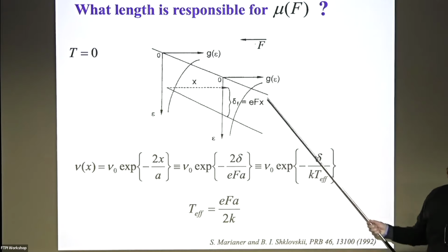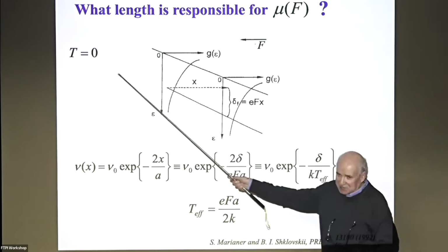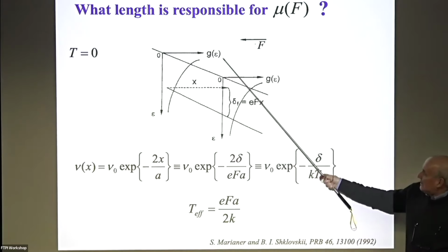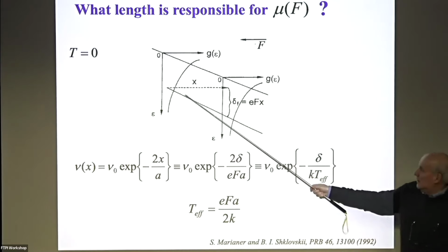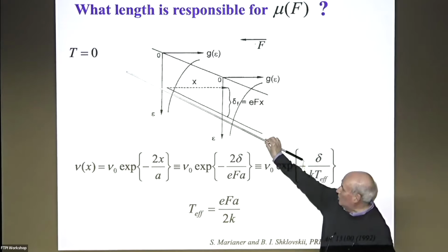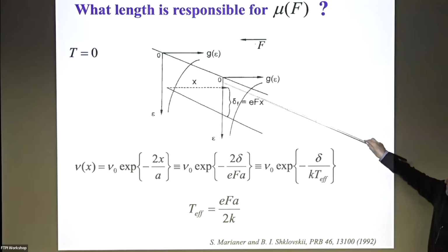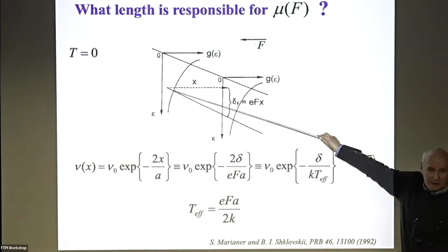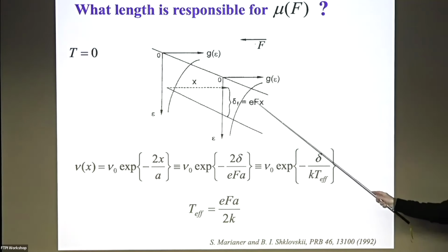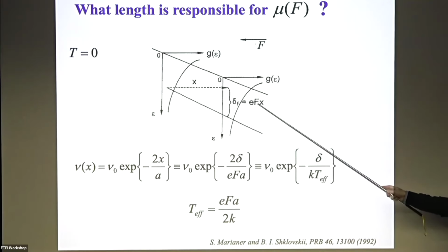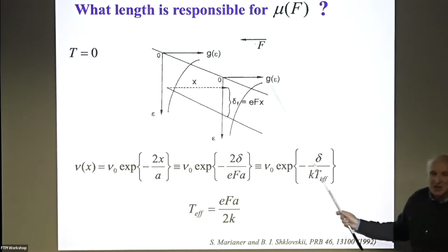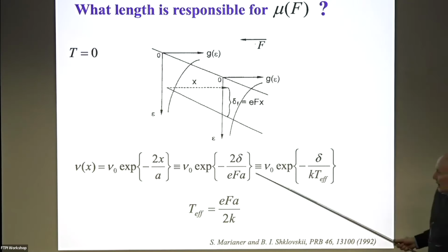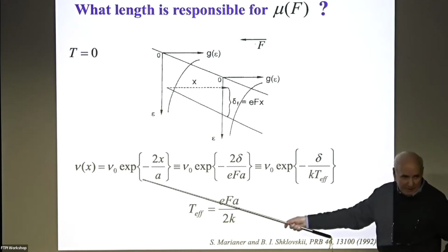Yesterday, all the students already informed us about it, so let's take temperature 0. Okay, then what happens? Let's take steeply decaying density of states. So electron tunnels from here to here, but because of the slope of the length scale due to electric field, electron appears higher with respect to the reference point as in the previous starting site. How much higher? It's just charge times field times x, and x is the intersite distance, so electron tunnels between the sites. The probability of tunneling is this one.